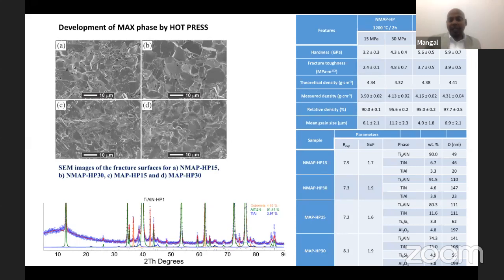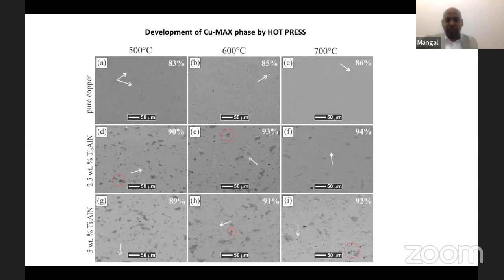Nanostructure in the sense you can take particle shape, or fiber, or flakes, or two-dimensional materials like graphene, MXene, or MAX phase materials. So we incorporated the MAX materials in the copper matrix. Unexpectedly, we much improved the mechanical properties, especially the hardness of the materials. And you can see the uniform distribution of the copper MAX composites with improved mechanical properties. That too we fabricated in the hot press.